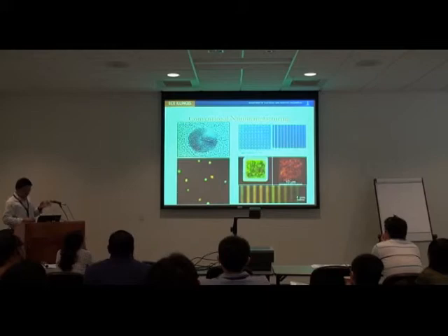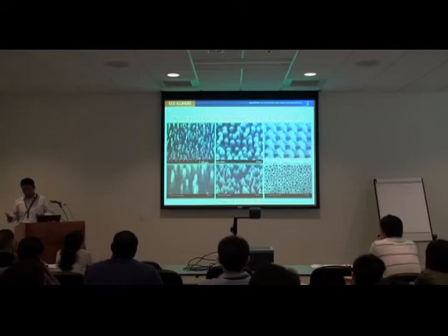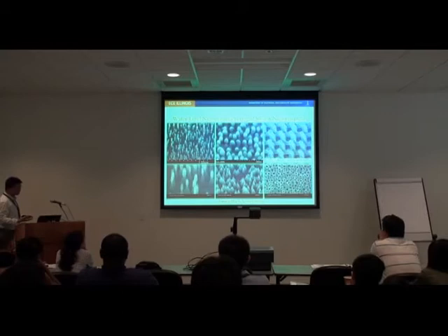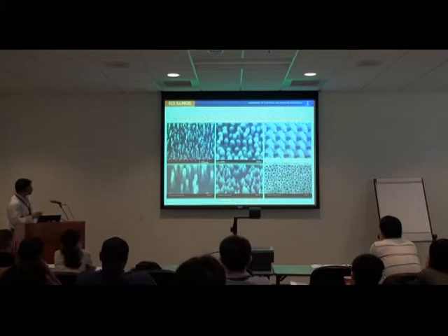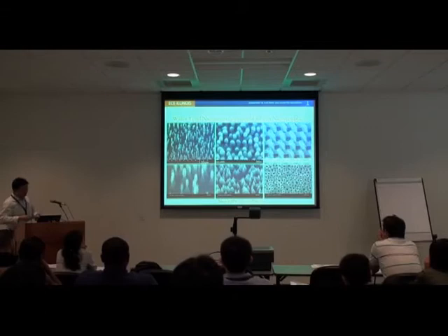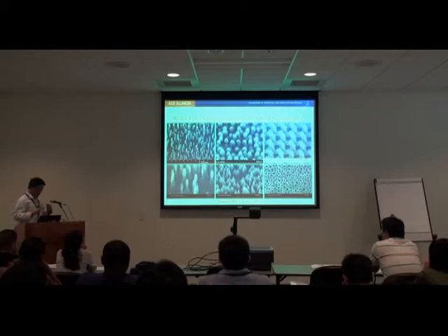But in my lab, we are now focusing on unconventional manufacturing at wafer level, which is also compatible with current semiconductor foundry technologies. So we're not only able to make them here, but also in the clean room at Santa Clara, Intel. This is a way we are investigating that technology can directly adapt into industry. So far we have figured out a way to make it at wafer level, thinking about 4-inch or 6-inch wafers, with the whole surface covered with a high density of different geometries of nanostructures. We build this on silicon wafers, make this nano template first, and then deposit metal on the surface.